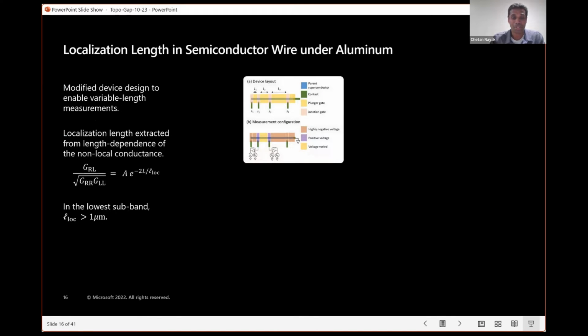We confirm this by actually measuring directly the localization length underneath the aluminum. We modified our device design a little bit so that, instead of having 2 tunnel junctions, we have 4 of varying lengths, so that we can measure non-local conductances, or transconductances, between different pairs of leads, and thereby in the same wire measure the conductance across different lengths. That non-local conductance is the derivative of the current at the right junction with respect to the voltage of the left junction, normalized by the local conductances. It is supposed to decay exponentially with the length of the wire, which we can vary by choosing different pairs of junctions.